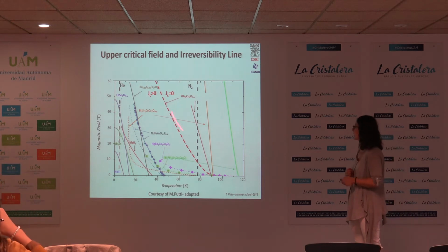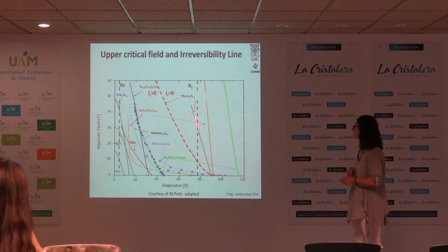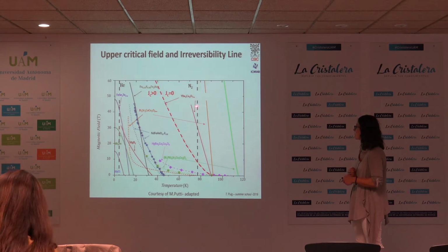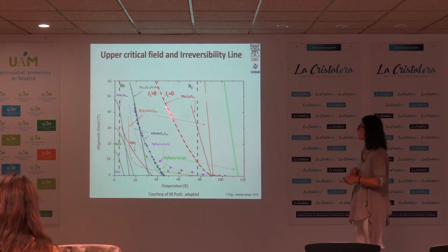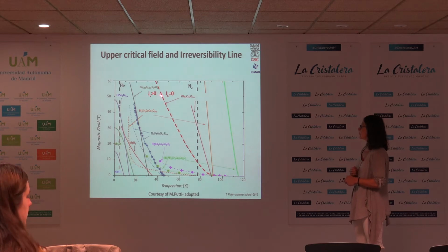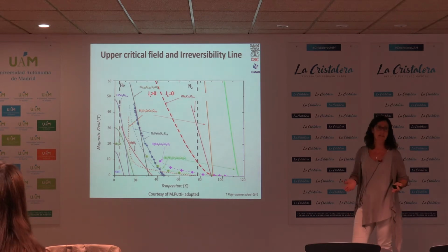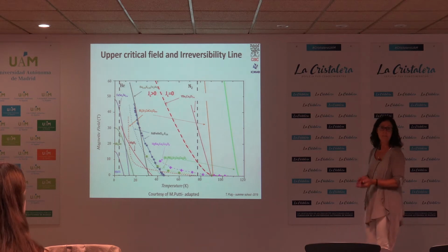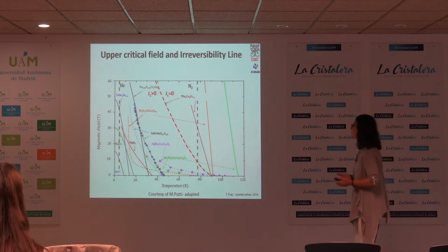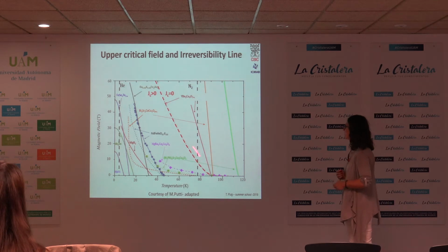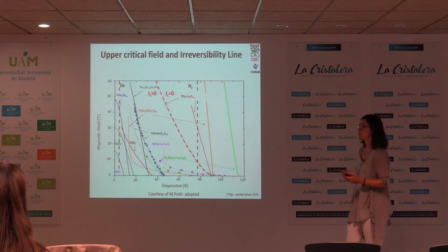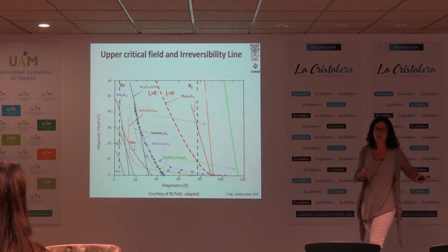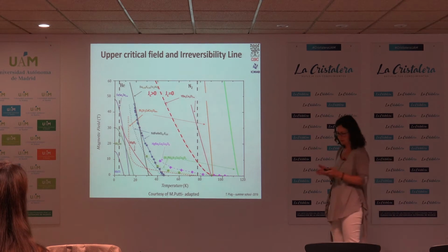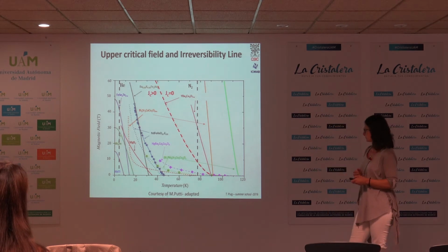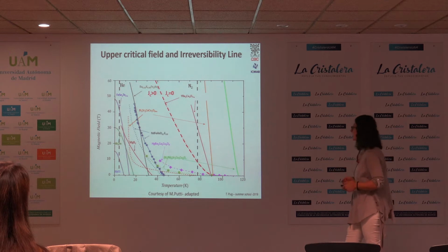So the irreversibility line is the line which is below HC2. This is the case of YBCO, the cuprate, so this should be HC2. This is the irreversibility line, which defines the area below which the critical current density is higher than 0, and above which is 0, and therefore for applications, at the end, the important line is the irreversibility line. And as you see here, TC and the irreversibility line do not match, and therefore not all materials which have high TC have high irreversibility lines, and there is the first compromise that we have to take.